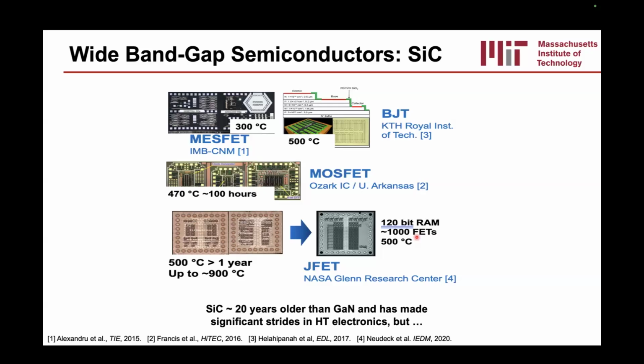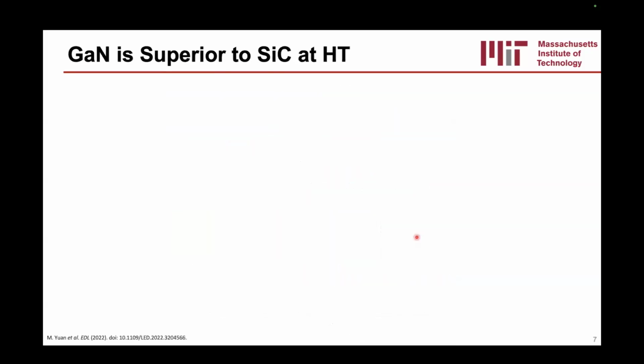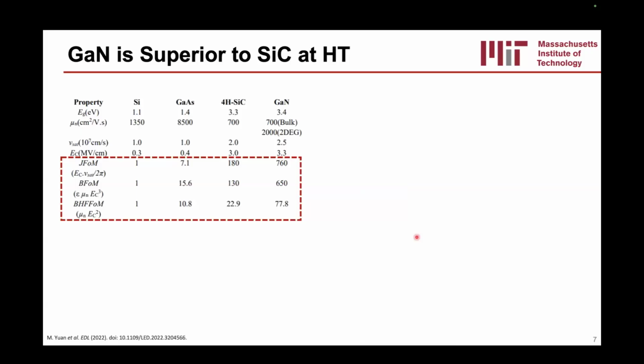And this is, once again, from a fundamental point of view. To begin with, even at room temperature, GaN has much better material properties than silicon carbide. If you look at things like the mobility, the saturation velocity, the critical field, which are really important device or material level parameters, GaN always has a much higher version of that compared to silicon carbide. And this translates to about 4 to 5X in a lot of figures of merit at room temperature. And a lot of this continues at high temperatures too.